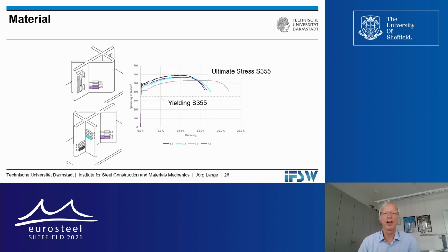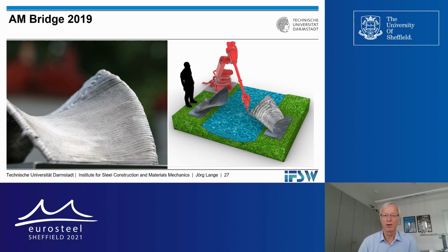Here you see this A-shaped test specimen, and you see how we cut some coupons out of that, and we get yield strengths above the 355, which was our goal, and ultimate stress also much higher than is needed for S355. And you see we get quite good strain results, 15 to 20%. So for that 3D printed material, in the direction of the printing or orthogonal to the printing direction, we get very good results, better than we expected.